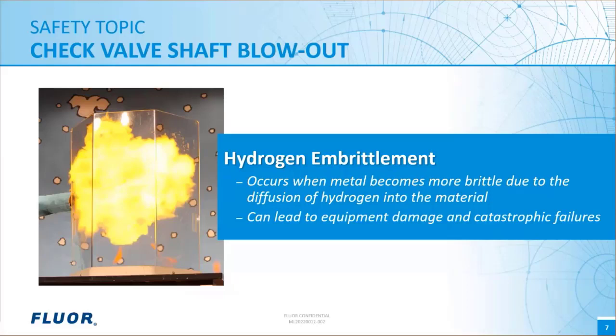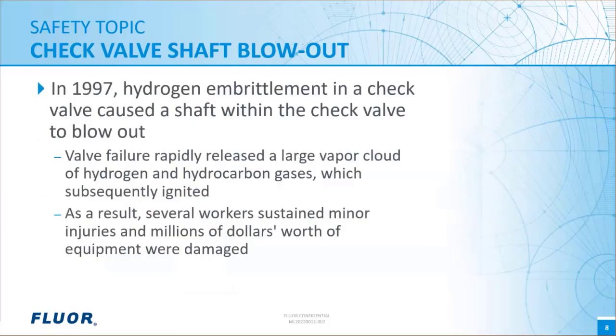Hydrogen embrittlement is an important condition to consider when looking at hydrogen systems. It refers to the condition when metal becomes more brittle due to the diffusion of hydrogen into the material. And when materials become more brittle, there's a higher chance of cracking and leakage, and this can lead to equipment damage. And as we know, hydrogen is highly combustible, so if leakages occur, explosions can occur and the failures can be catastrophic. And this is exactly what happened in 1997.